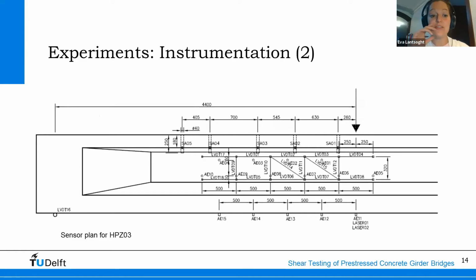Here is the sensor plan for one of the experiments. It varied a little bit among the experiments, but gives you an idea. We have the grid of LVDTs to find the strains and deformations. We have the positions of the acoustic emission measurements, 15 in total. We have the laser distance finders under the position of the load. And then, it's not shown here, but on the other side of the specimen, we have the speckle pattern, and we take photographs to do the digital image correlation.